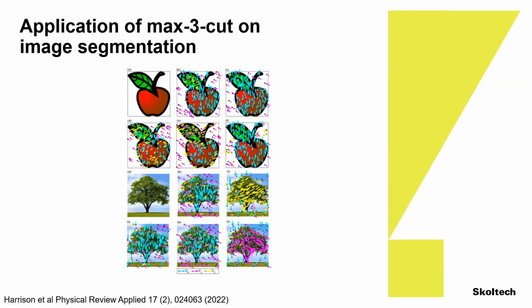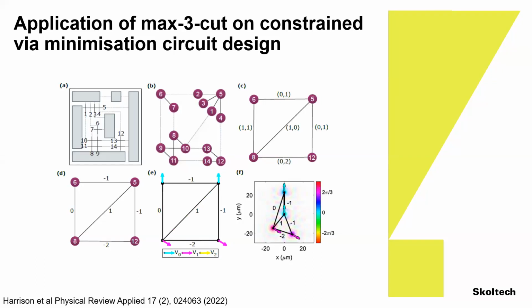Then we can apply it to the max 3-cut problem. So this is the max 3-cut on constraint via minimization circuit design that comes to your phones and your computers. There are actually the circuit boards that we have. In order to reduce the cost, you want to minimize the number of bridges, the number of crossings that you have between wires. And of course, we don't have just one plaquette. We have stacked plaquettes, and you want to minimize the number of bridges between the plaquettes. And we did the same thing here. We mapped the system onto our lattice of polariton condensates, and we found out that actually our system can give us the optimum solution to the problem.